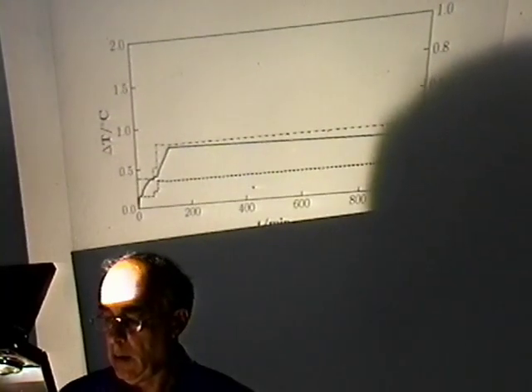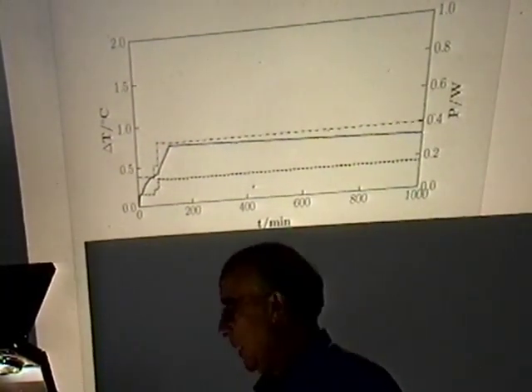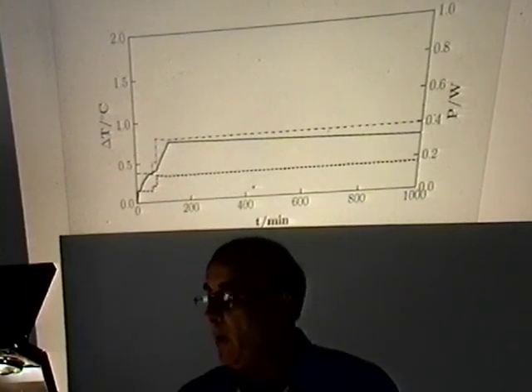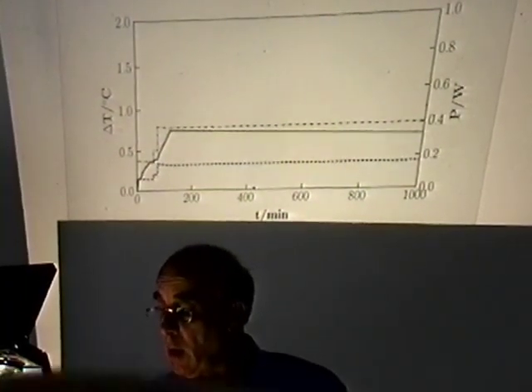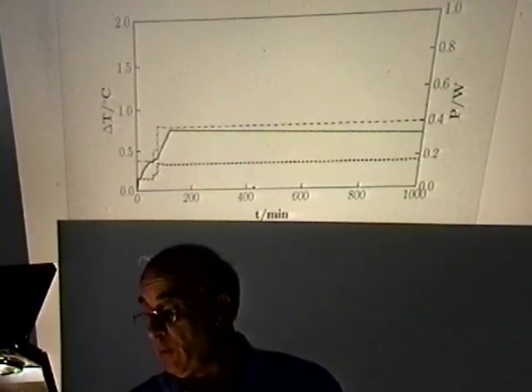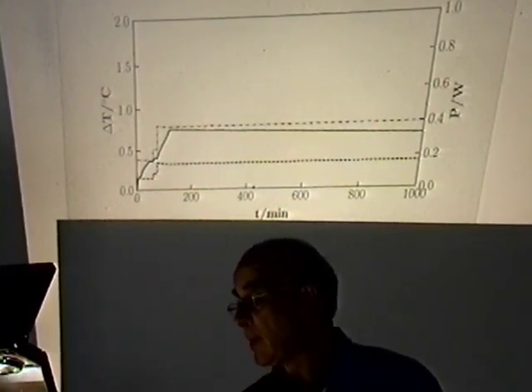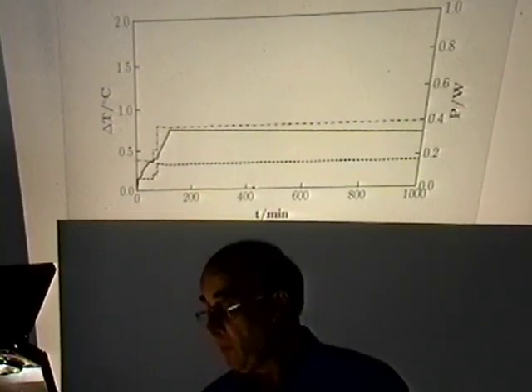Well, the samples which were giving behavior 1, that is, an immediately decaying potential transient, were giving no thermal effect. With the sample of type 2, this one, which had a dimension of about 5, a surface of between 5 and 6 square centimeters.